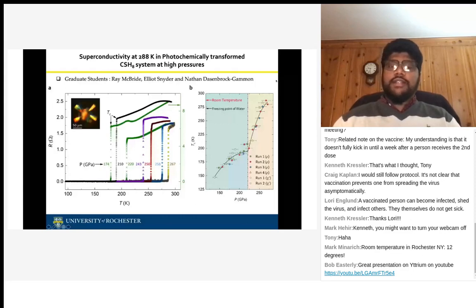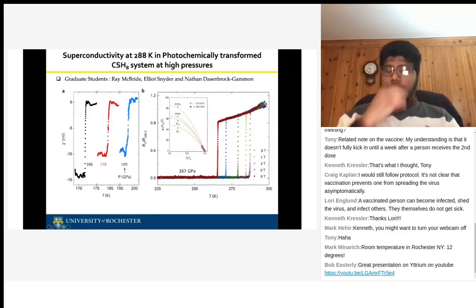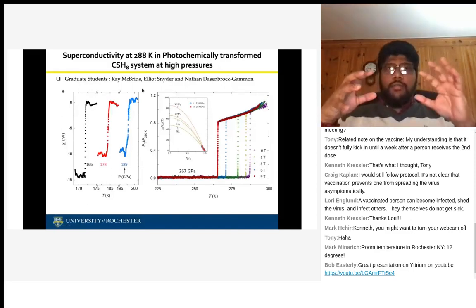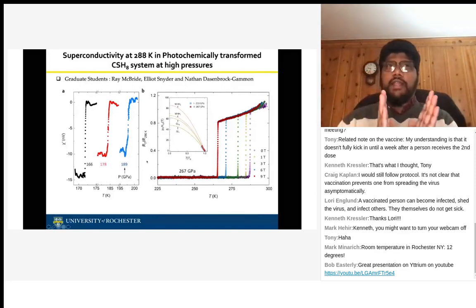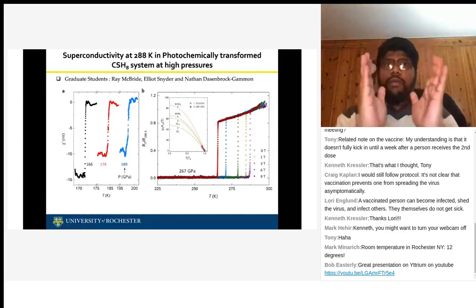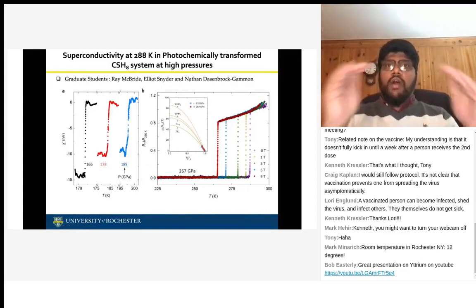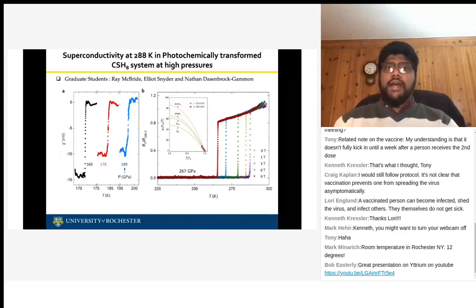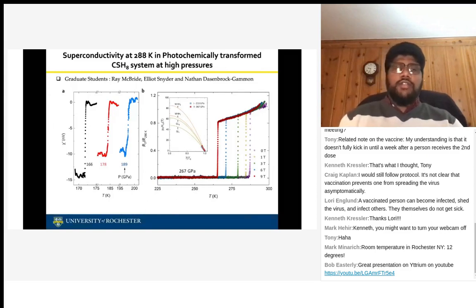So the electrical resistance study shows that your electrical resistance vanishes, goes to zero at room temperature around 267 gigapascals. So in order to prove this, we use two other techniques. One is magnetic susceptibility measurements. As I said before, when you apply a magnetic field to a superconductor, instead of going through the sample, it goes around it, which means it acts as a diamagnetic material. So you can measure the magnetic susceptibility, which indicates it is going through a superconducting transition.